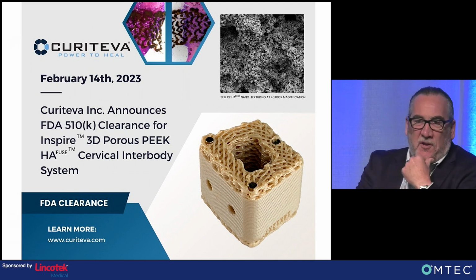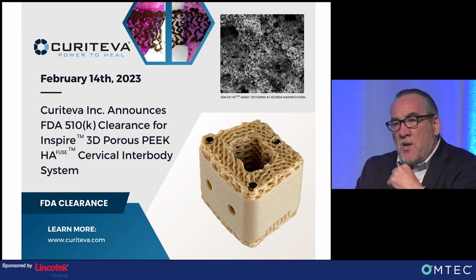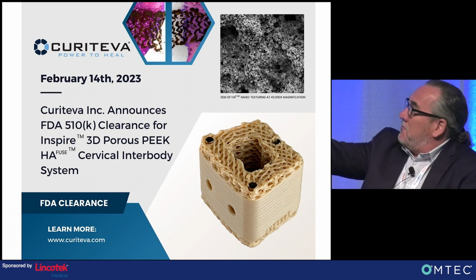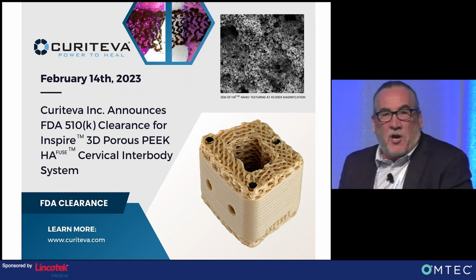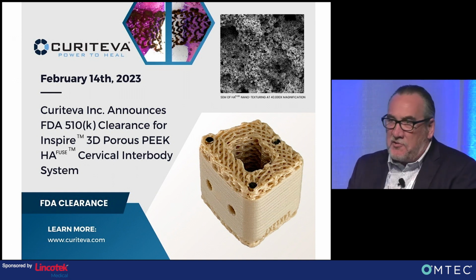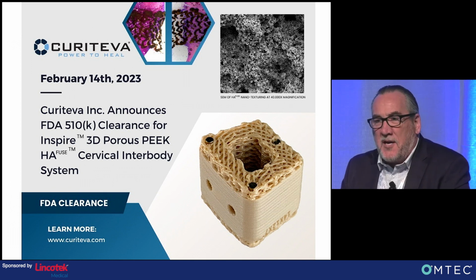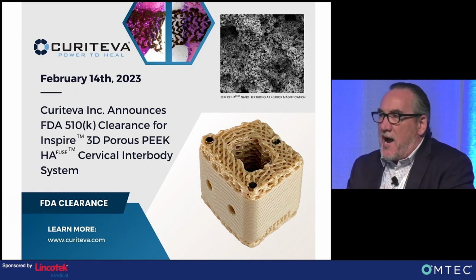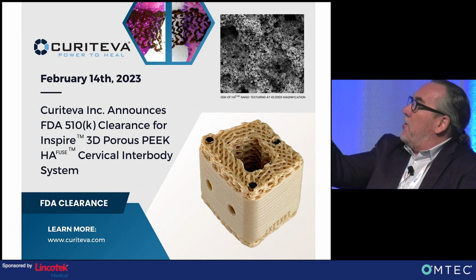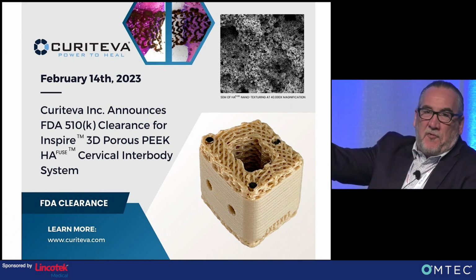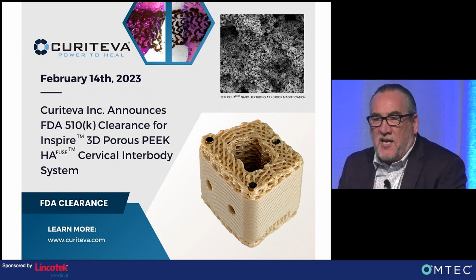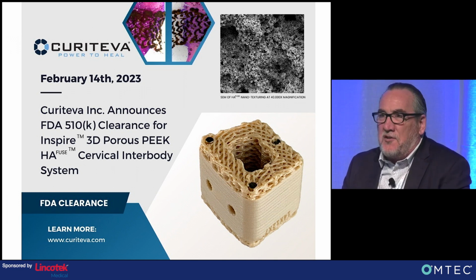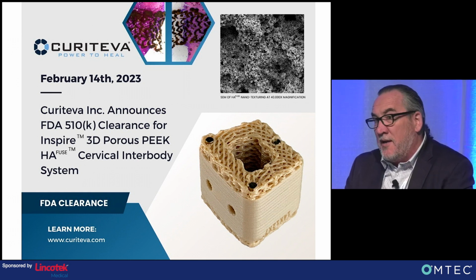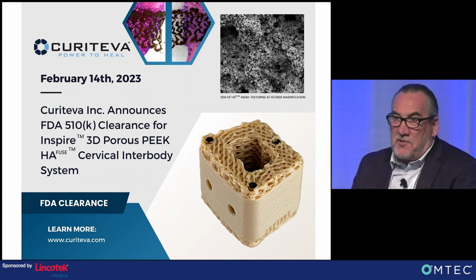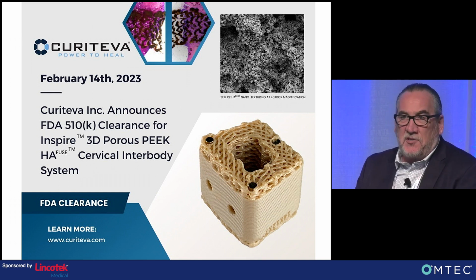And so a couple more things I'll say, and then I'll hand it back over. The image on the right is to the biomaterials group. This is a nano coating that's on there. It's a hydroxyapatite, calcium deficient hydroxyapatite. ProMimic has cultivated this technology for over a decade. It helps drive the biologic interface. And in the middle here, you can see a histology section courtesy of Professor Walsh, and a model that's been published extensively. And the pink or the red that you see there is bone growing completely through that implant. And I can tell you there's literally no fibrous tissue in there, which is uncharacteristic for PEEK.